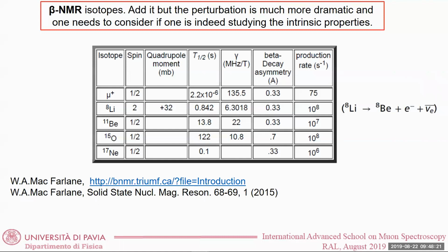Mostly because of the time scale of your relaxation times: the spin-lattice relaxation rate scales with gamma squared. Since the gamma of the muon is about 3 times that of protons, you get a factor of 10. But this is just to give you an idea, because it depends a lot on the type of experiment you are doing.